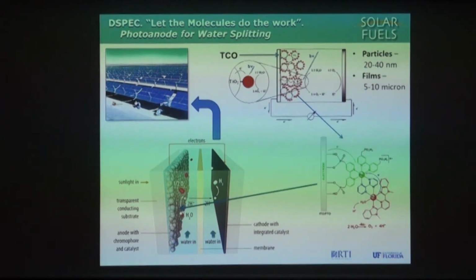This is kind of an artist's rendition. You need a transparent conducting oxide backing. Then on top of that is a film of these nanoparticles. And this film is probably, say, 10 microns thick, 10 to 15 microns. It then is decorated on the outside by these chemically bound magic molecules. If you then translate that with light excitation and have one of these chromophore catalyst assemblies, so you get injection followed by activation,